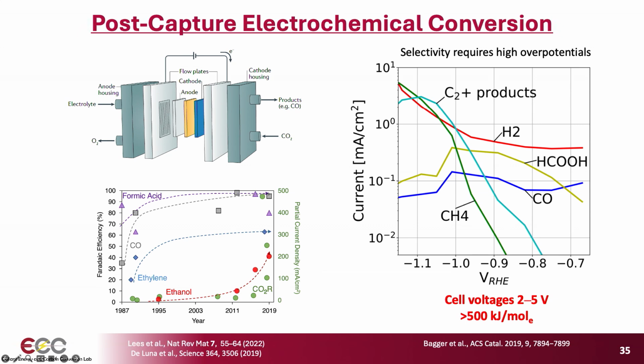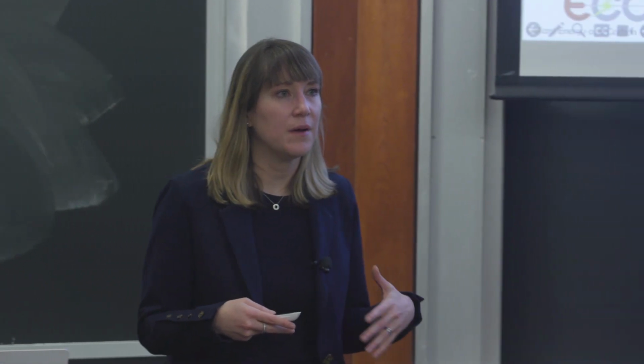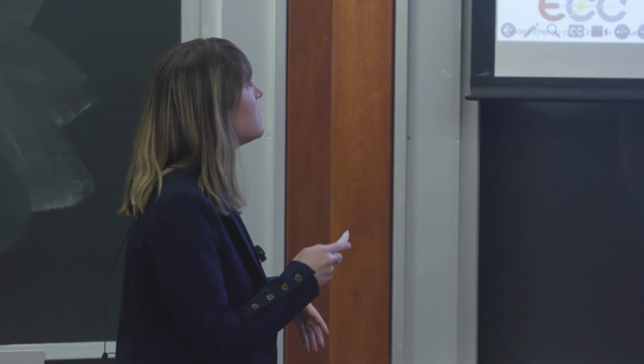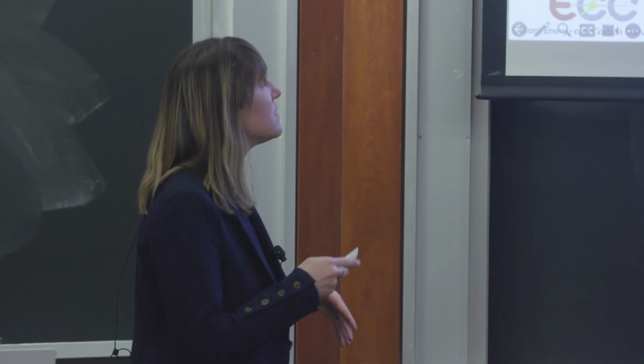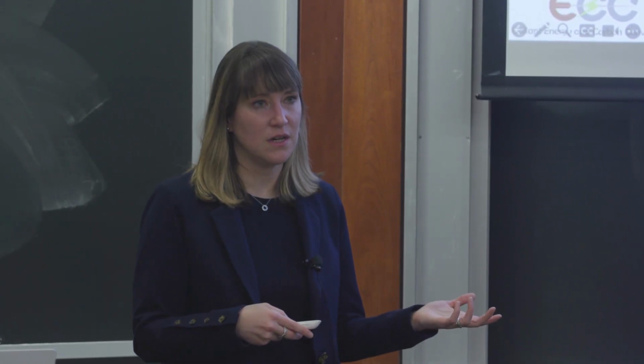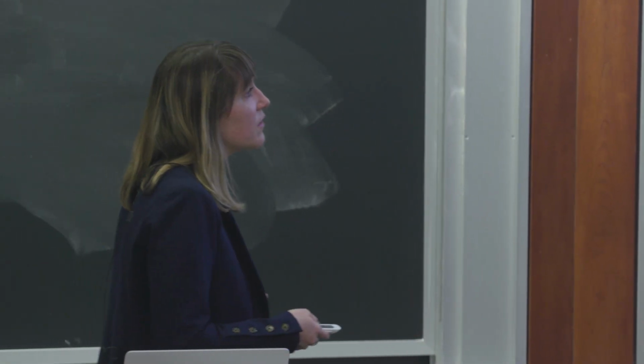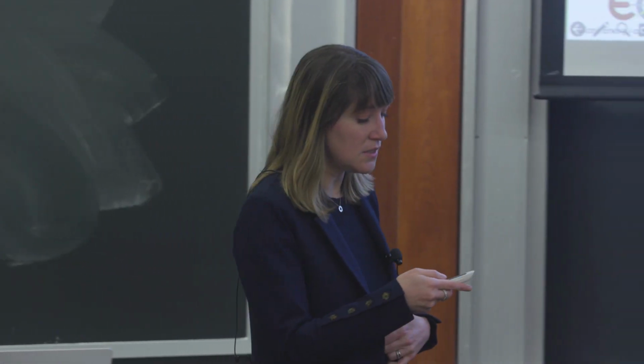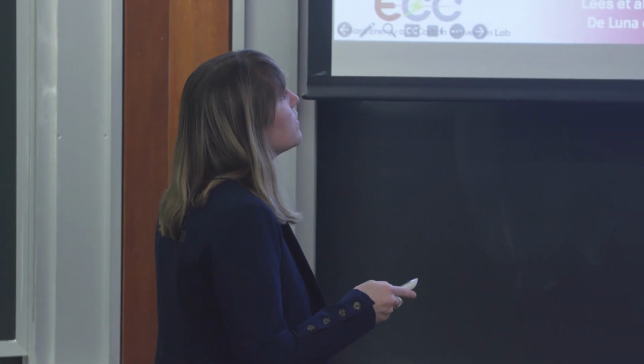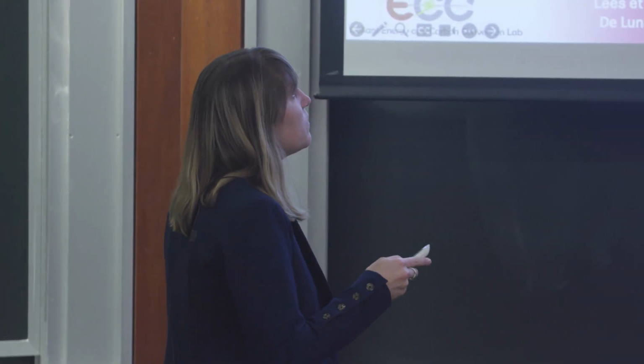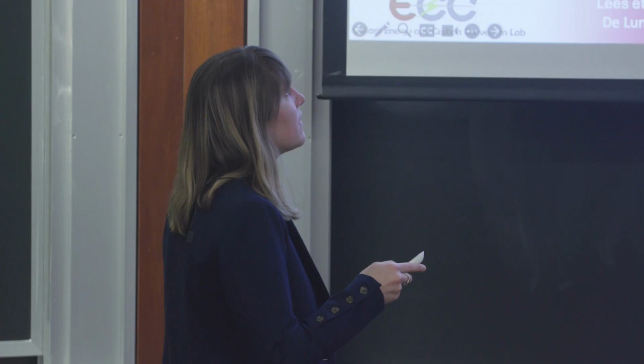And one thing I want to emphasize here is that wherever you have a Faradaic efficiency less than 100, the balance is made up usually, at least in a major sense, of parasitic hydrogen evolution. So this is just a parasitic process due to water reduction that's running in the background and can often actually dominate your reaction. And we very often have to go to highly reducing potentials in order to compete with this parasitic reaction and actually get products in excess of the hydrogen.